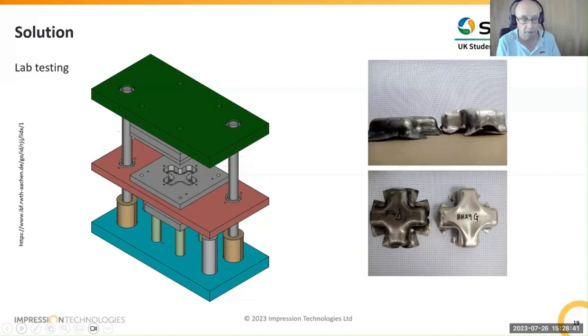On the left hand side, you've got a schematic of the tooling, with the punch at the bottom, with a blank holder plate, which we sit the blank on, and then the punch comes down from above, and we can measure the load on the press that we do this on. So we run at the same temperatures, and we can run at the same speeds as we do in production. And there's examples of some of the parts that come off that particular tool on the right hand side. We can measure depth of draw, and we can also take the load data that comes off the equipment and plot load against draw and rank lubricants that way.